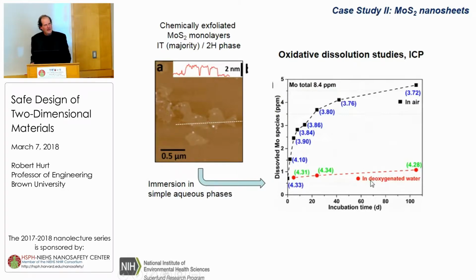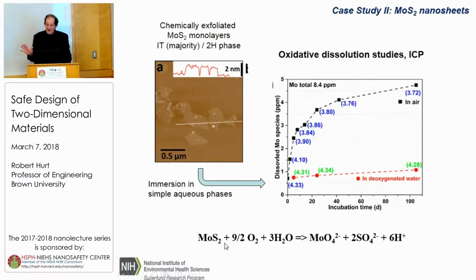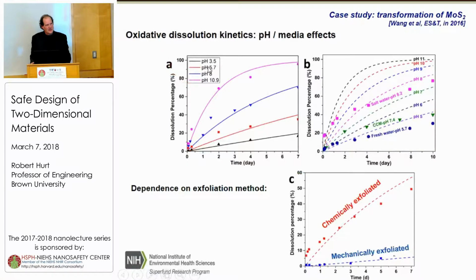If you do the whole thing in deoxygenated water, you see a much lower rate. And this is likely just due to residual oxygen in the sample. So this is, according to our prediction as well, an oxygen-mediated oxidative dissolution of molybdenum disulfide. It's slow. It requires aqueous phases. It requires dilute conditions, but it's real. And it would very likely render this material non-persistent. And it produces molybdate and, of course, protons.